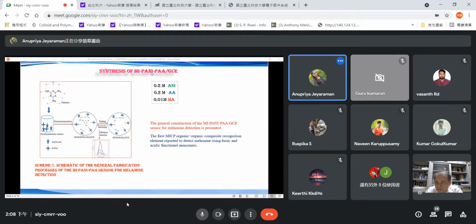Synthesis of melamine, polyaniline, and polyacrylic acid. Here, 0.2 mole of aniline and 0.2 mole of acrylic acid in the presence of 0.01 mole of melamine, in the electropolymerization process under a sweeping potential carried out from 0.2 to 1.0 volt. Scan rate was performed at 100 mV per second, 10 cycles to form the MIP polyacrylic acid GCE.